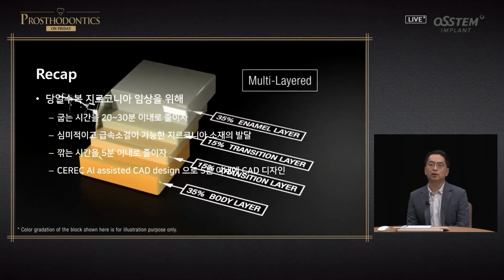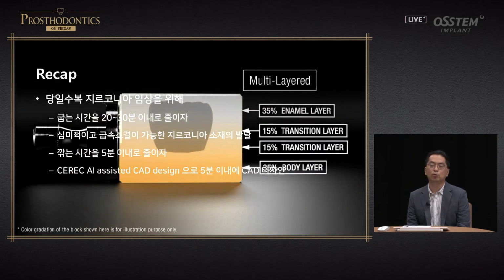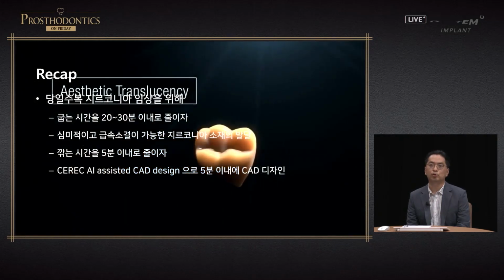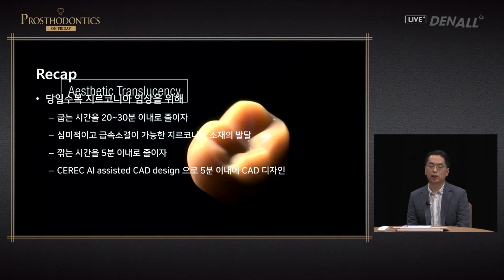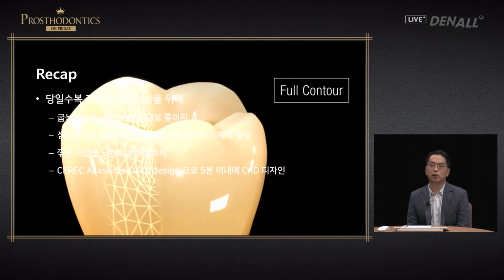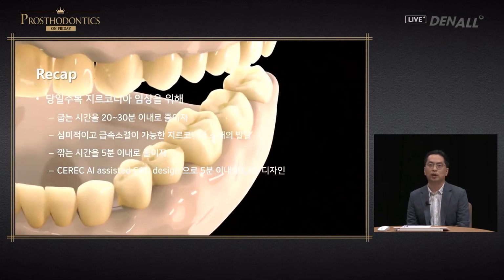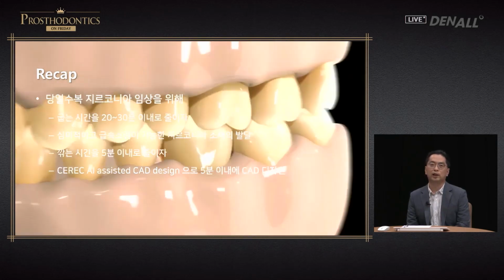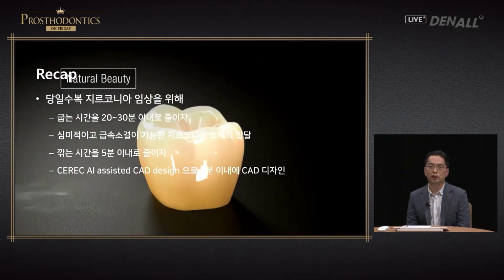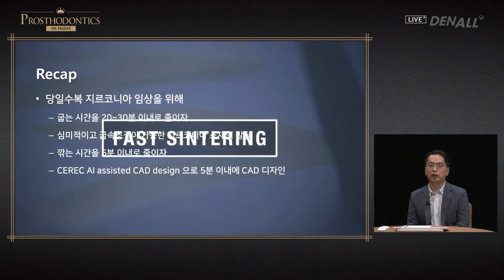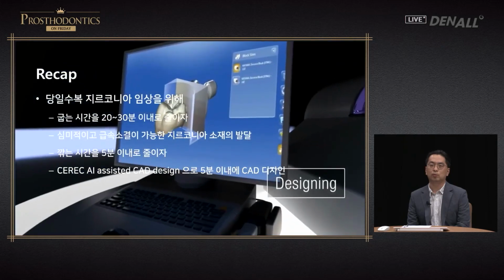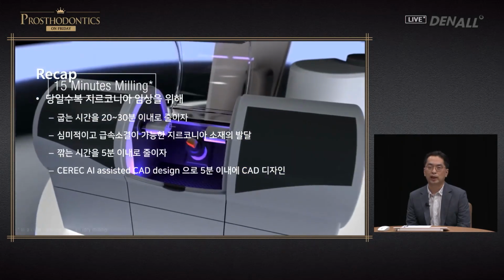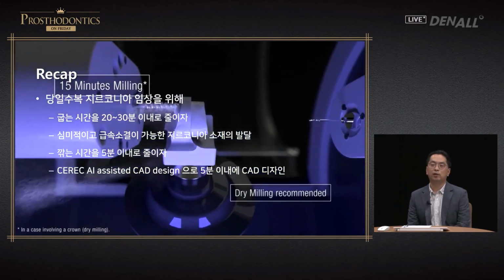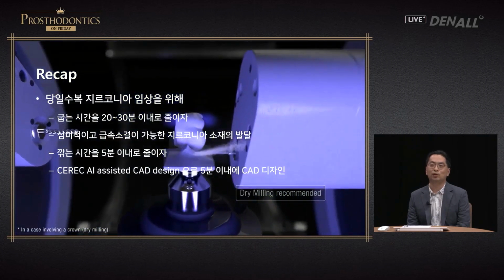If you can reduce the time for milling a single crown to within 5 minutes, you can provide a one-day zirconia crown within 30 minutes. In my dental clinic, when the patient goes through endodontic treatment, before doing the endo treatment, I scan the natural tooth. The reason is after endo treatment, you need to provide post-crown restoration. If you can mimic the original tooth form, that'll be best.